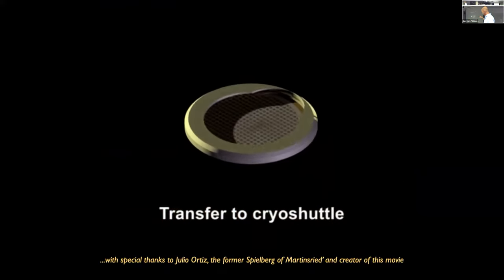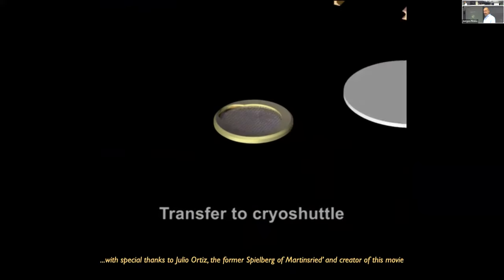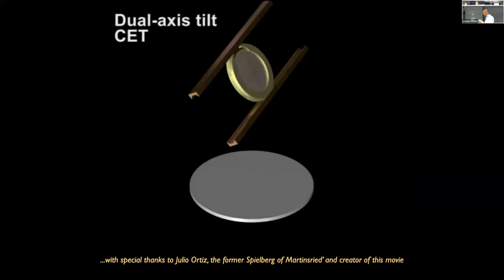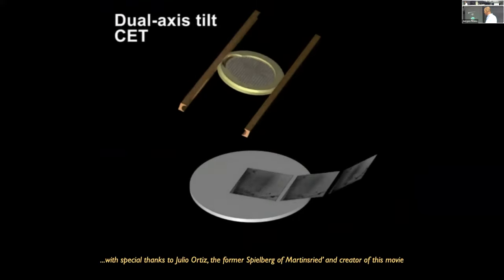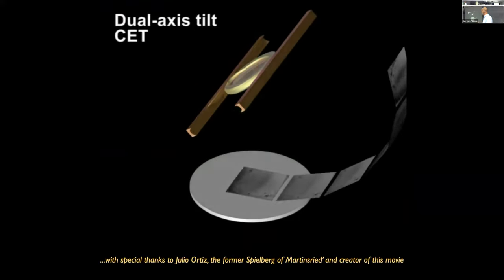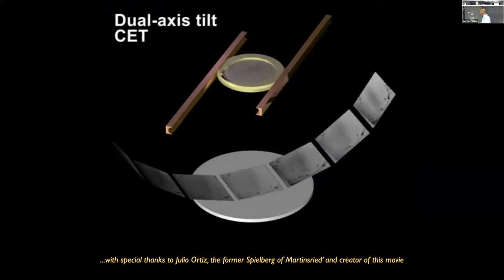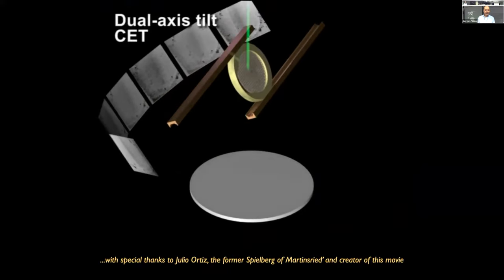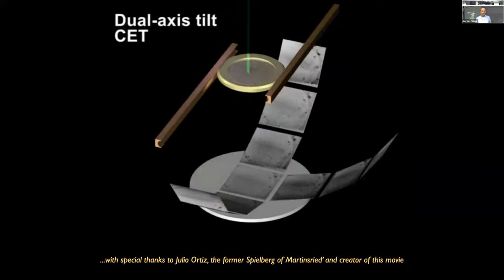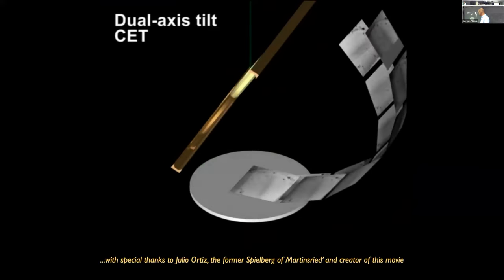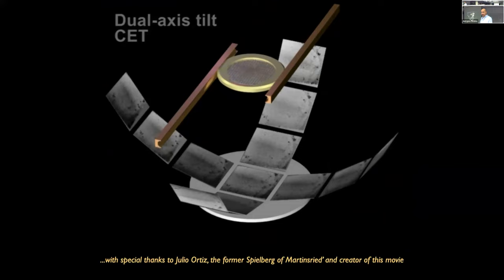And you see that these autogrids have an indent, a slot, so that you can allow shallow milling from shallow angles. And then you take a tomogram. At that time the idea was dual axis tilting, which is nowadays not really pursued. You need to increase the information content of the tomogram, but the alignment of the two series and the radiation damage is prohibiting high resolution. Anyhow, that was at that time, but you see the chopsticks of a Titan or a Glacios or whatever we have for dual axis tilting.